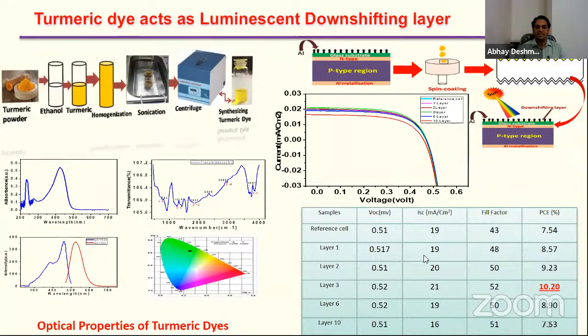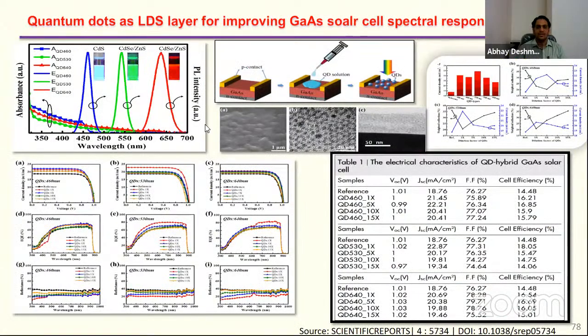And now if you see the current, the ISC was earlier 19 and fill factor is 43. Here fill factor has increased, VOC increased, and the maximum current increased from 19 to 21. So even a 2 milliampere current increase has given me an efficiency of 10.2 from 7.5. So even if you increase the current or VOC, ultimately your output power will increase, and that will increase your percentage conversion efficiency. So even for gallium arsenide, CdS, CdSe-ZnS have been tried with